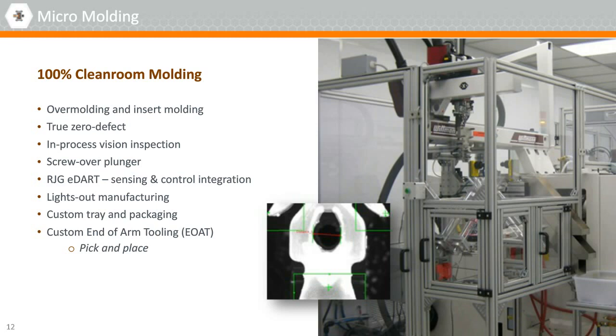But in MTD's case, the screw only melts, feeds, and conveys the polymer into the plunger cavity. This has several advantages, but the most basic are controlling residence time at high heat and not shearing all of the material in the barrel for every single shot, as it would commonly do in conventional molding.